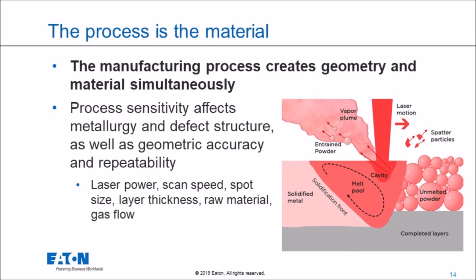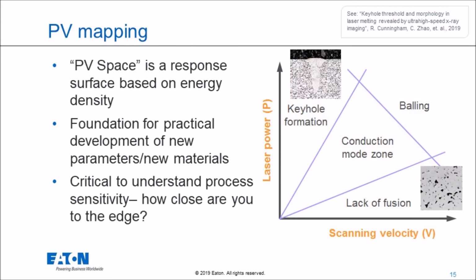And just to drive this point home, if you work in this industry, you've probably seen this before. This is called a PV map or a PV space, PV being power and velocity. This is essentially a 2D representation of a response surface of what is actually happening in the powder bed fusion process. On the vertical axis, you have laser power, and on the horizontal axis, you have scanning velocity. This is one of the ways you determine your process sensitivity from two of the main inputs into the process, which are power and velocity. So if you put too much power into the part and don't go fast enough, that depression in the melt pool goes too deep, and you get holes, porosity in the part because you put too much power in.